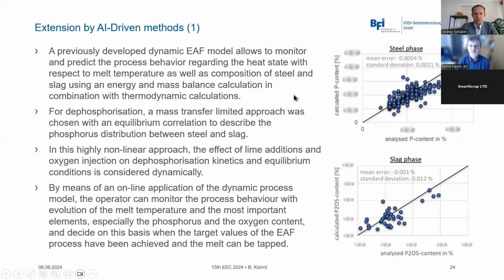So, for example, for dephosphorization, we have used the mass transfer limited approach with an equilibrium correlation to describe the phosphorus distribution between steel and slag, which is an important parameter for dephosphorization. And in this highly nonlinear approach, we also have to consider the effect of lime additions and oxygen injection on the dephosphorization kinetics and the equilibrium conditions.